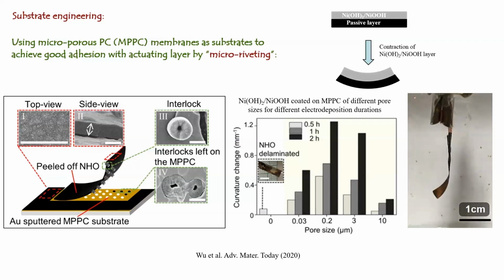Okay, so by doing that, let's say this is such an assembly of materials, you can see that it can bend to a radius of curvature of around one millimeter, which is quite useful in a lot of applications. And in terms of how much curvature the system can sustain, if you do not have any pores, basically it cannot sustain a lot of bending. Delamination will easily occur, but with the pores, the bending can be enhanced a lot.